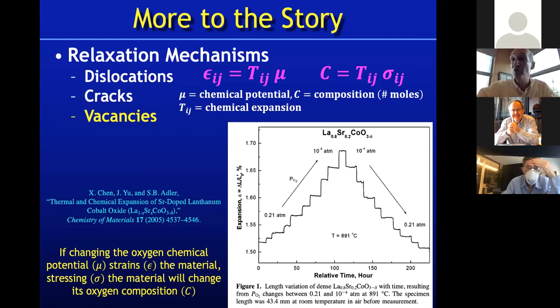behavior of strontium cobalt oxide, which my multiferroic friends got interested in, but from an experimental standpoint, that's a lot of pressure to try to make in a vacuum system. Anyway, strontium cobalt oxide is hard to make because it's hard to make cobalt in the 4+ state. And similarly, if you take even lanthanum strontium cobalt oxide and you put it in vacuum, so if you go from being in air to being in vacuum, and you're patient, notice that the time scale here, this is a bulk sample, but the time scale here is in hours.